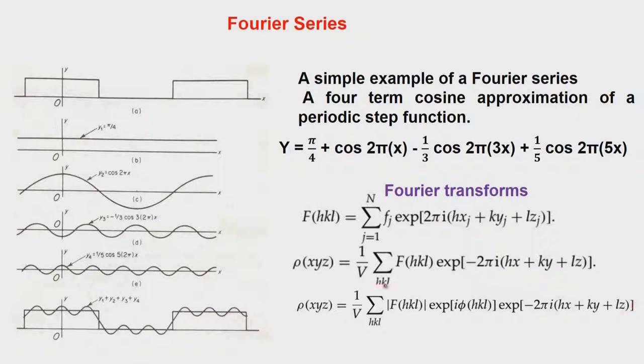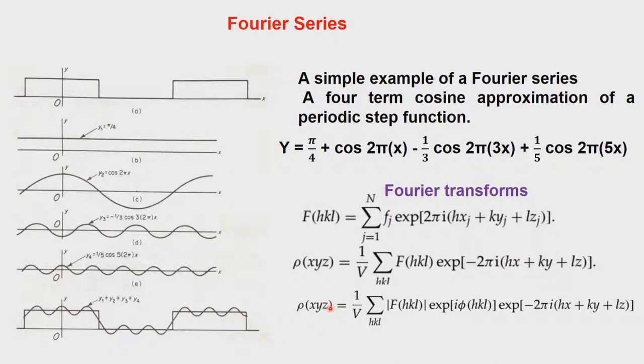This is the general expression for ρ(XYZ), which depends on the summation over all H, K, and L, times exponential(2πi(HX + KY + LZ)), which is a representation of the atom position XYZ. In principle, a perfect fit requires an integral over all HKL from minus infinity to plus infinity. But in a crystal, we have the advantage of limiting H, K, and L to certain values — so it is a triple summation replacing the triple integral. This three-dimensional summation takes the F(HKL) value, takes the phase into account, and therefore the electron density can be computed as a near-complete representation of the periodic function.